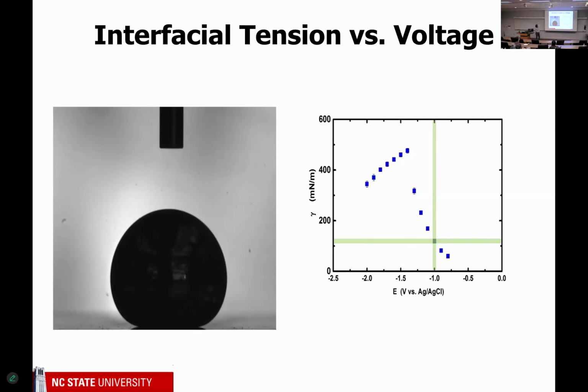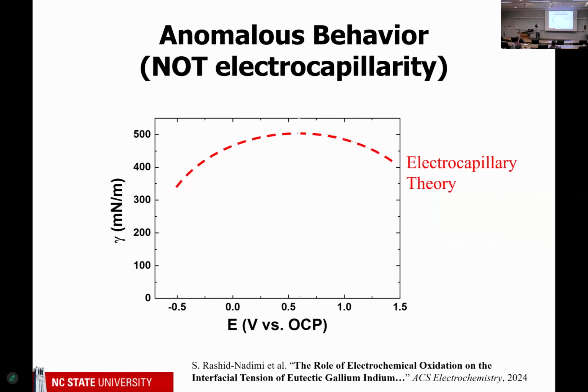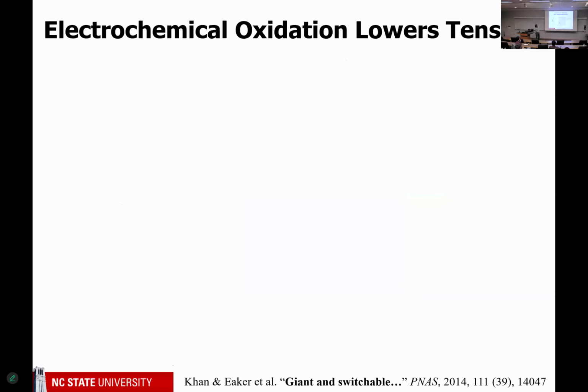Well, let me skip ahead. So if you take this data, and first of all, remember the theory predicts a parabola, like a capacitor. And so if you put some of our data on there, it follows the theory perfectly. It's acting like a capacitor. We're just putting charge at the interface. But as soon as we start to see oxidation, where you see electrochemical reactions occurring, we get this anomalous behavior where it drops very, very rapidly. And so it's not electrocapillarity, it's due to oxidation.